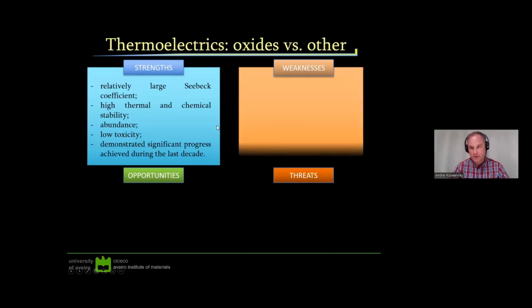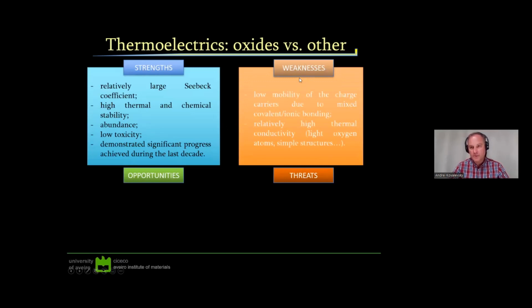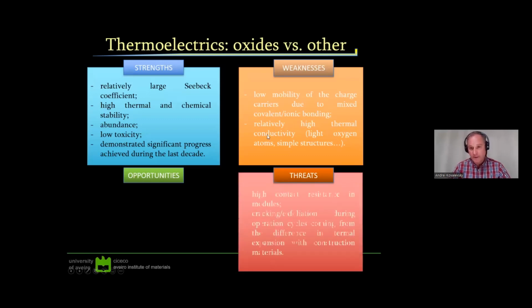The weaknesses related to oxides are low mobility of the charge carriers, due to mixed covalent-ionic bonding, and also relatively high thermal conductivity, because we're speaking about quite simple structures, at least compared to those traditional thermoelectrics. Also, every oxide contains oxygen, a light element, and light elements are not very good for low thermal conductivity.